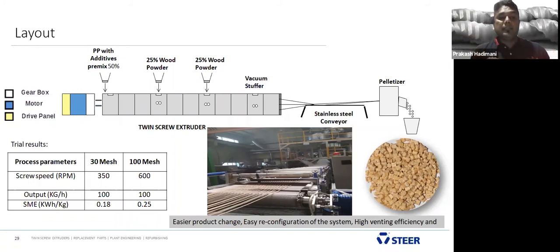With 100 mesh, the specific mechanical energy increased, but with 30 mesh, the specific energy reduced. And the mixing will take place because we have used two technologies: one is the standard bilobe technology, the second is FGT technology. The only change was in the screw; the feeding method and everything else were the same. Process parameters were changed, but we collected standard technology and FGT samples and tested them in an injection molding machine.